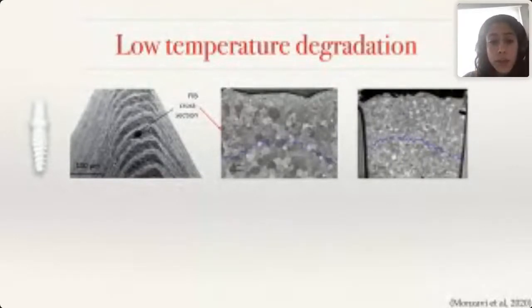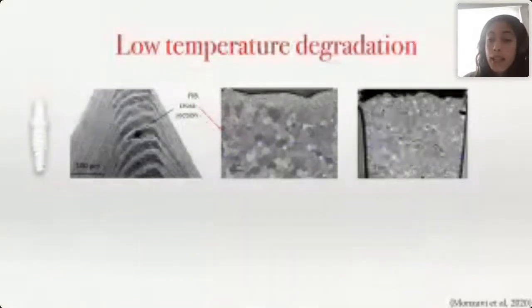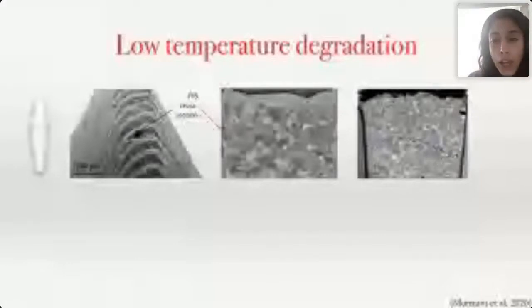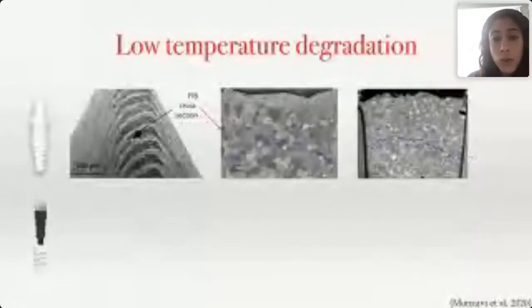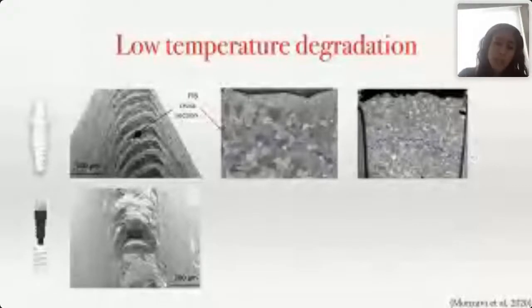In this particular group, there was some transformation to begin with because of the surface treatment, the laser surface treatment. After aging, there was some increased transformation, but very minimal, about 2 to 3 more microns. So it was not significant, even though it simulated about 60 years in the human body.